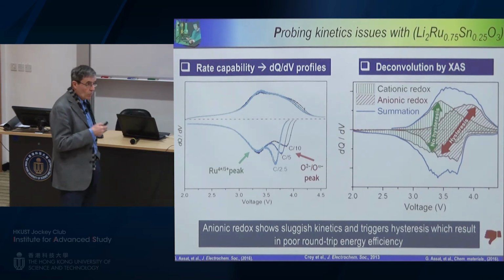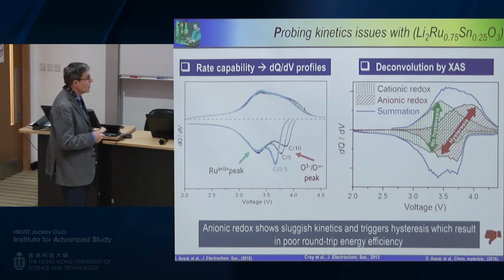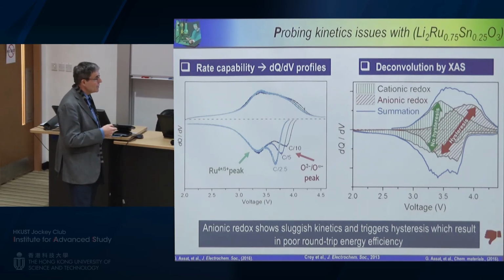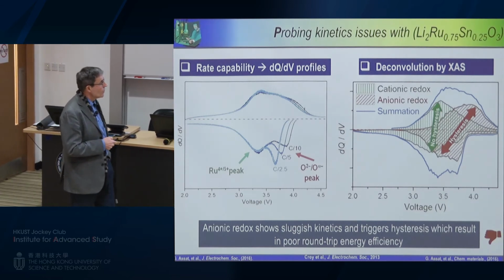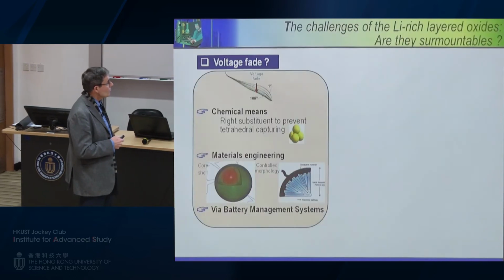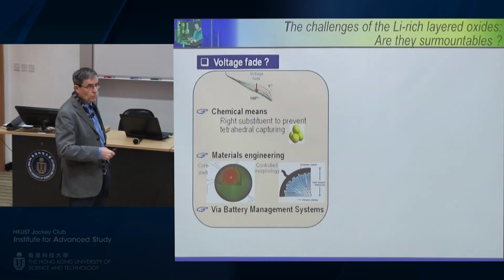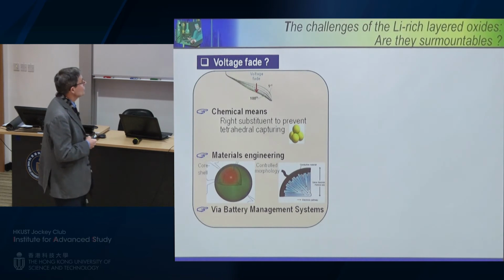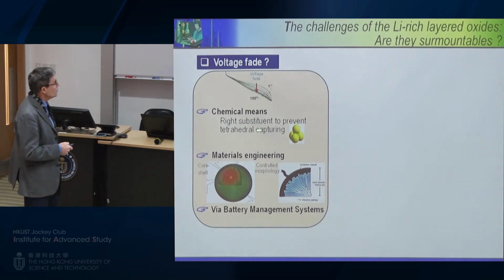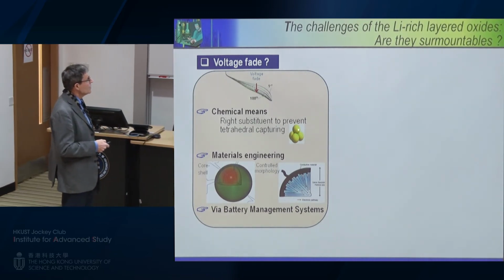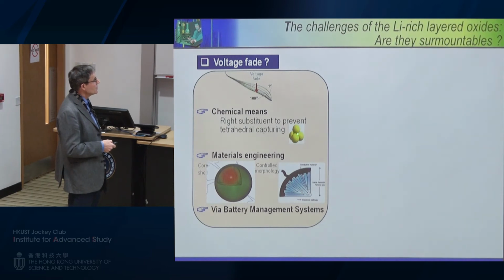So this is really one of the main issues of these materials, which is also identical for lithium-rich NMC. Now the question: can we overcome this issue? We can do it by chemical means. As I mentioned to you, in this case, use bigger substitution elements to not be trapped. We can also play with material engineering.